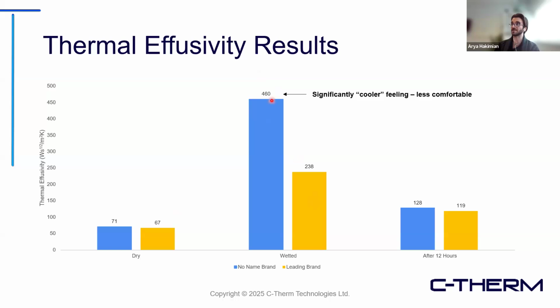So upon initial wetting, we do see that the no-name brand was significantly lower performing compared to that leading brand, even though they both started out very similar. And then looking 12 hours later, we do see, of course, it doesn't go quite back to baseline because there's still some partial saturation, but again, much more comparable than the initial wetting. But again, you'd say, is it worth paying the extra money for the leading brand versus the no-name brand? Well, maybe sometimes it is, sometimes it isn't, but just a quick data set illustrating where that might play a role.